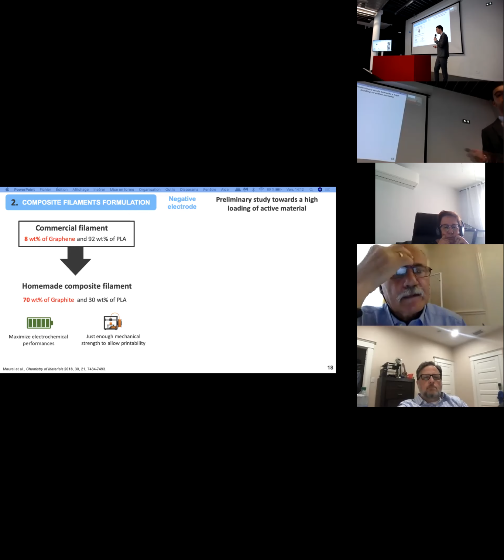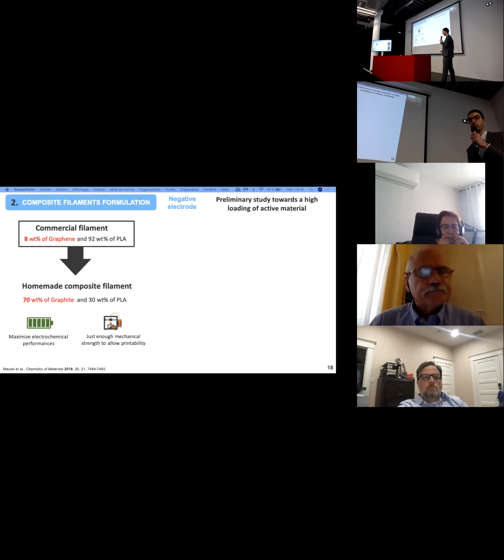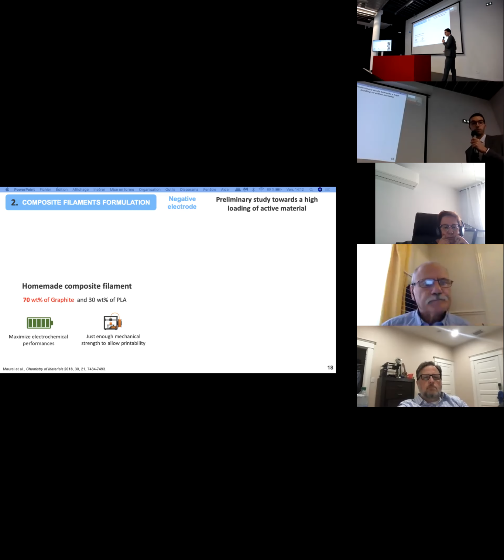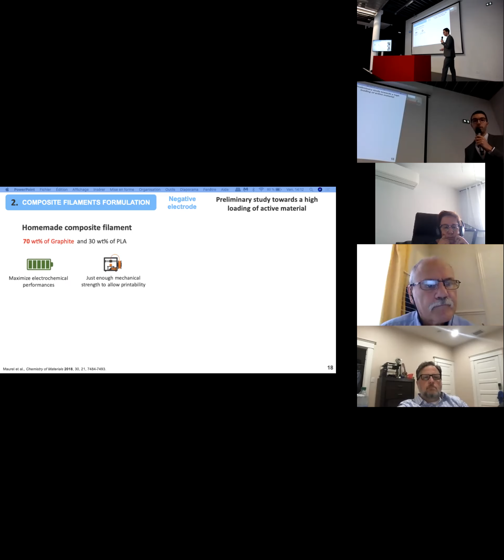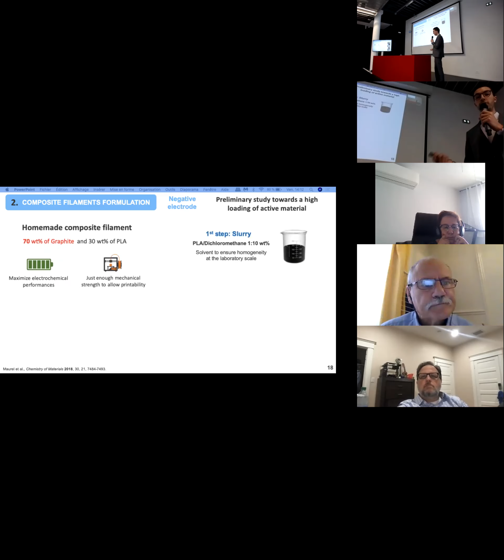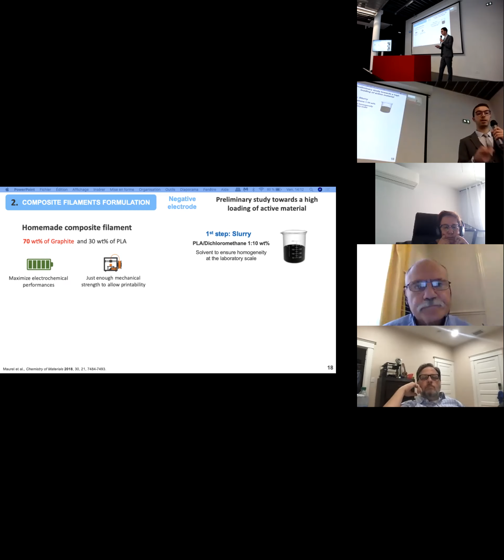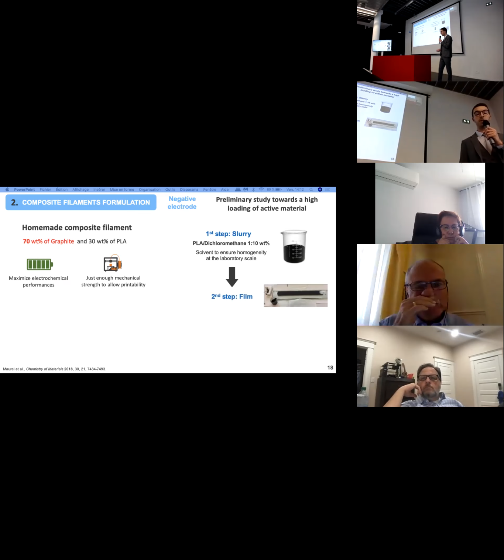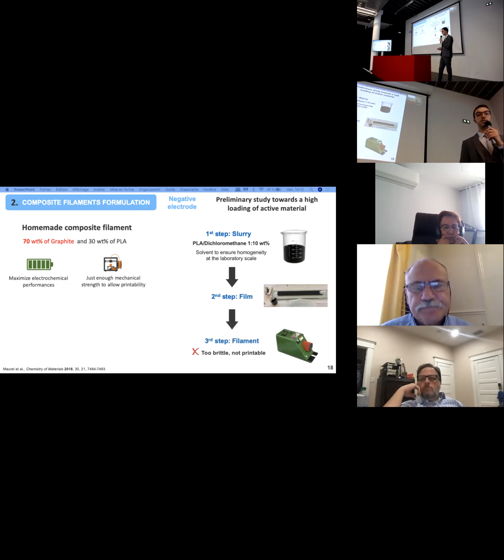So here, that was a huge amount of active material we tried to implement. So let's focus on this main filament that we tried to do. So first step, of course, slurry. We combine polymer matrix and graphite here in solvent. Here we use dichloromethane. Then we obtain a film, and this film we cut into tiny pieces in order to feed an extruder. Unfortunately, the resulting filament here, as you can see, was not printable at all.